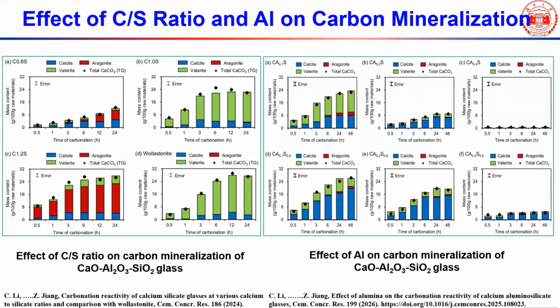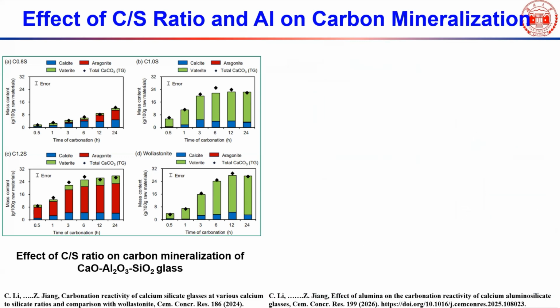The first graph basically shows how the calcium to silica ratio affects carbon mineralization. You can see if the calcium to silica ratio is very low, the carbon uptake is also low. On the other hand, if you increase the calcium to silica ratio, then the carbon uptake increases. Those are glass materials.